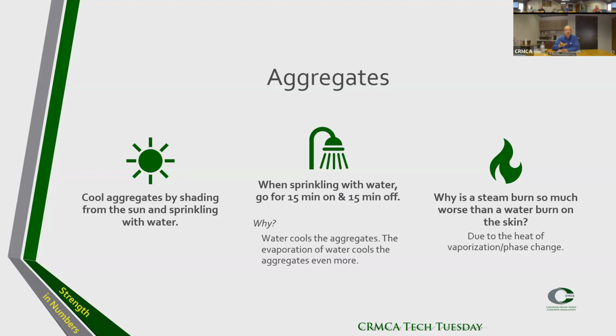And evaporation is a change from liquid to vapor water, and this actually takes more heat out of the aggregate pile. It's the same reason a steam burn is much worse than a water burn: because of the heat change from the vaporization phase change. So just something to consider. If you need to sprinkle the aggregates, save some water. Go to Home Depot or Lowe's, get a timer for your sprinkler and save some water, and likely get better cooling out of your pile.